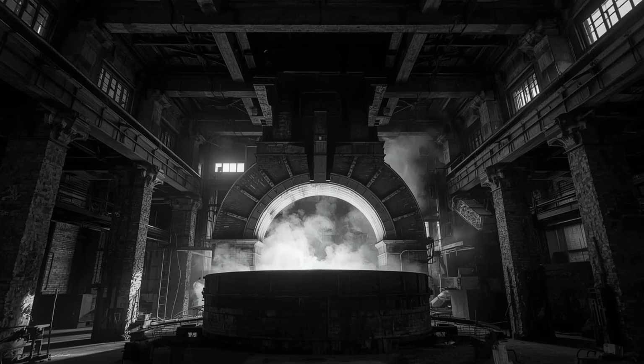The picture that emerges is one of multiple effects working in concert: moisture-driven shrinkage, constrained thermal expansion, creep under load, iron band compression, thermal stratification, and internal pressure. No single effect dominates. Instead, they combine, each amplifying the others, creating a net result that appears simple. The furnace is getting shorter, but that arises from a complex interplay of material behavior under extreme conditions.